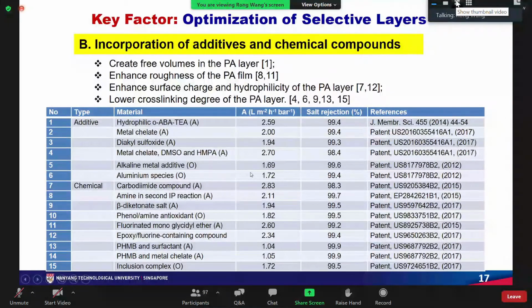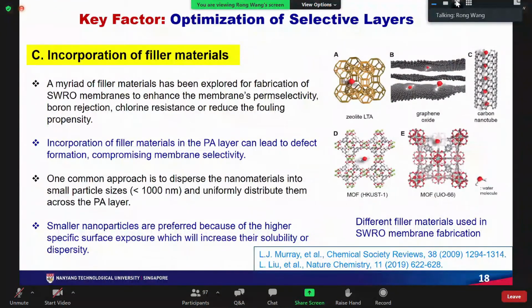Okay, in addition to the formula, people also try to use different additive and chemical compounds to affect the interfacial polymerization. Those chemicals and additives we found are reported in the patent. I list this patent here for your information. Different types of filler materials like zeolite, graphene oxide, carbon nanotube, MOF, etc. have been widely used to make thin film nanocomposite SWRO membranes to enhance the membrane selectivity, boron rejection, chlorine resistance, or reduce membrane fouling, etc.